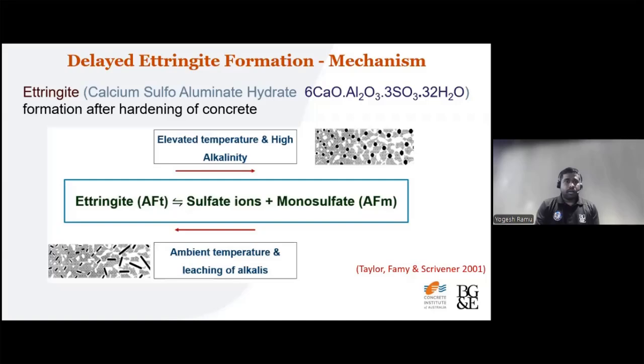It doesn't harm the concrete. In fact, it has some benefits to the concrete. So that is not an issue, but the issue is that ettringite is highly unstable when it comes to resisting high temperatures. So if the concrete is hydrating at very high temperature, say anything above 70 to 80 degrees Celsius, the ettringite can disintegrate and decompose to monosulfate and sulfate ions in the concrete.